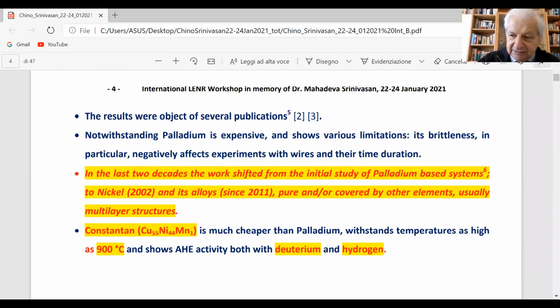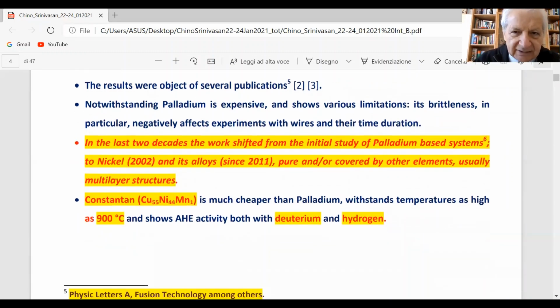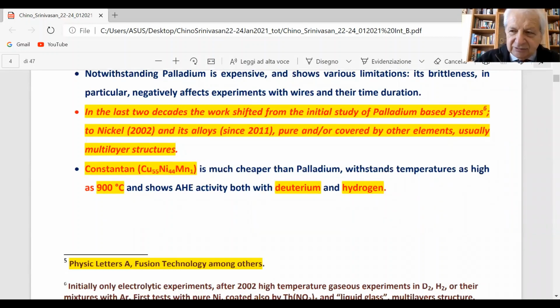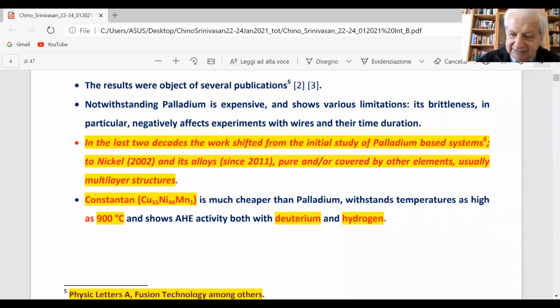The experiments with pulse were a variant of the palladium plate used by Professor Takahashi. The results about pulsing were published for the first time in '94, '95, in very famous journals like Fusion Technology. So it's a well-established method, but we had to stop such procedure because of the weak aspect of palladium, that makes powders even after hydrogen absorption. So it's a very, very strong problem.